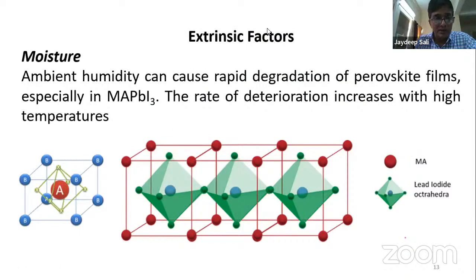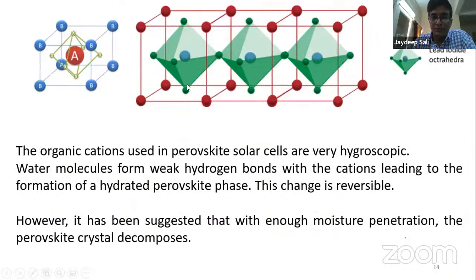Now, this is a typical crystalline structure of a perovskite. Moisture present in the ambient, that is, ambient humidity, can cause degradation of the perovskite films. Specifically, this is MAPbI3, methyl ammonium lead triiodide. This is a typical perovskite that is being used widely in solar cell fabrication at a research level. The rate of deterioration because of moisture also increases with temperature. Now, there are various reasons behind this deterioration.